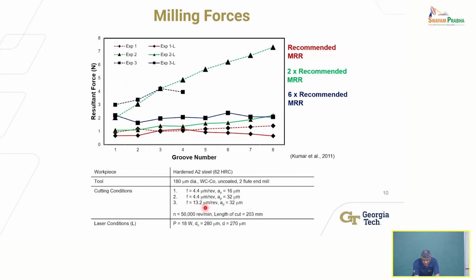The feed is on the order of 13 microns per revolution, which doesn't sound like a lot, but it's a lot for a small tool. Okay. And the depth of cut is 32 microns, the axial depth of cut, which is more than number 1, right? The feed and depth of cut are much smaller there. So here, without any laser assist, it failed after 4.